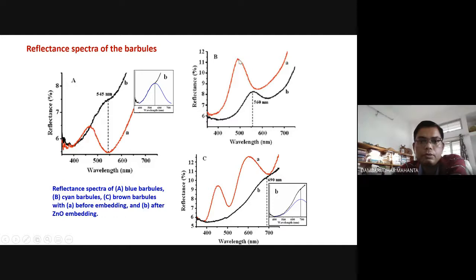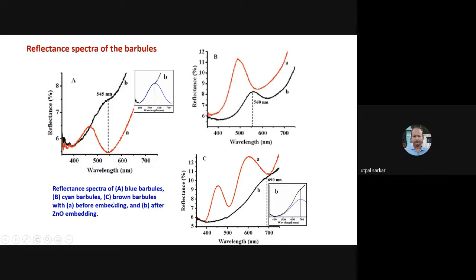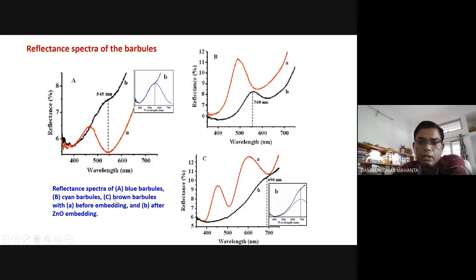Now for B, you have cyan, which is around 485 or so. Then it has also shifted to 560 nanometer. Finally, brown or yellow-brown color, you could see here there is a Fabry-Perot etalon kind of thing. You have two stop bands, in fact. One is here, one is here. Now, after zinc oxide loading, this has gone.